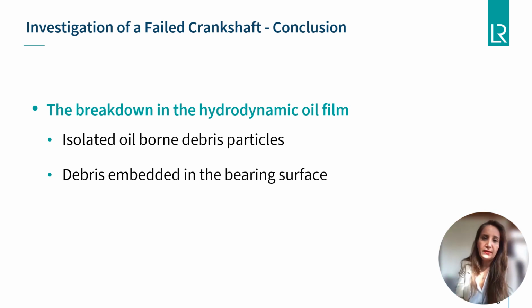It is thought that the breakdown of the hydrodynamic oil film between the bearing and journals caused the wear and spalling observed. These areas then acted as a stress concentrator for fatigue crack initiation. It is likely that the presence of oil-borne debris particles and/or debris embedded in the bearing surface resulted in the formation of hotspots leading to wear and spalling. The spalled particles can then significantly exacerbate further wear and abrasion, leading to formation of fatigue cracks.